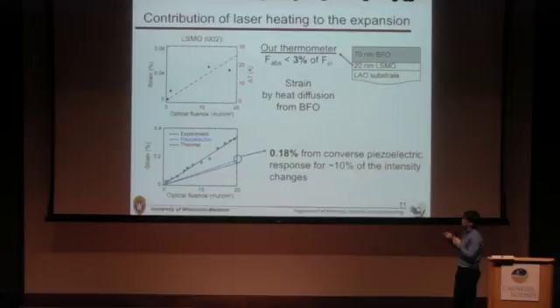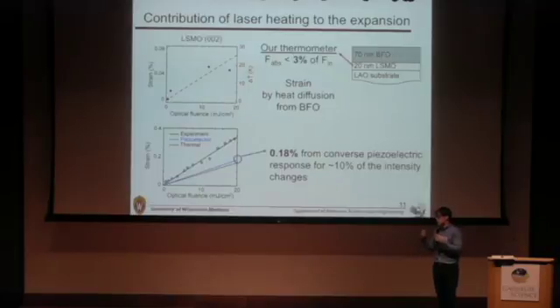So we think this strain arrives from heat diffusion, and we convert this strain to the temperature increase, and by using the heat from this temperature increase, we estimate the heat in the bismuth ferrite by doing the heat diffusion analysis. And we got the thermally induced strain here, indicated by the red line, and got how much piezoelectric response can be induced with the experimentally determined strain. And it was 0.18%, which is quite close to the electrically driven strain. So we conclude that a similar magnitude of structural transformation is necessary to see the phase transitions, which is electrically driven.